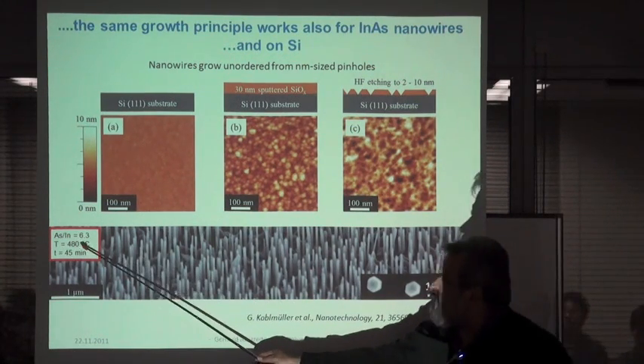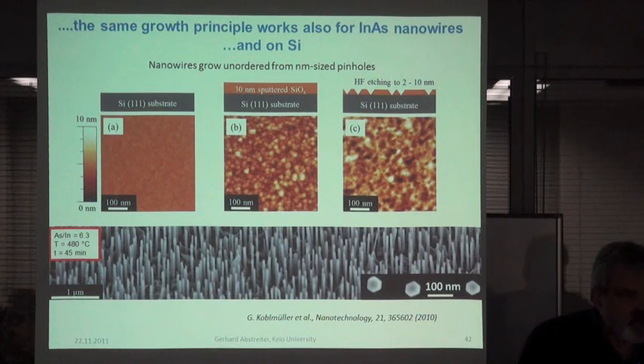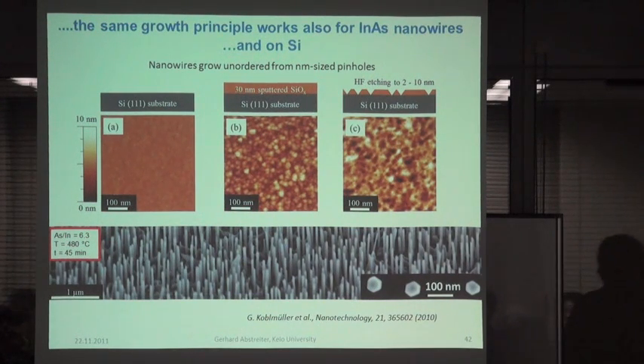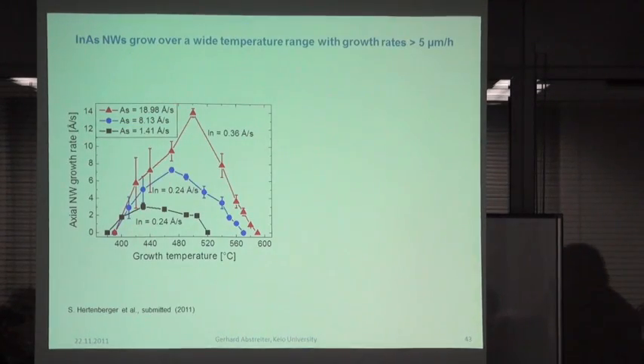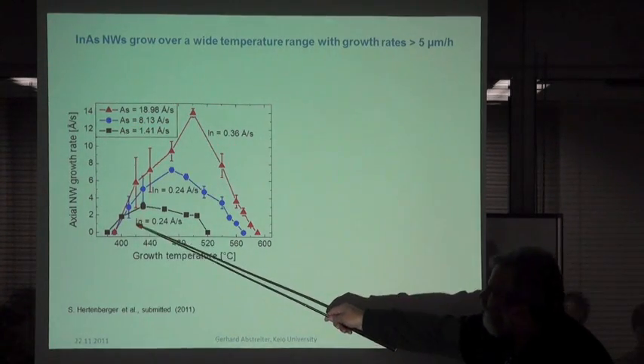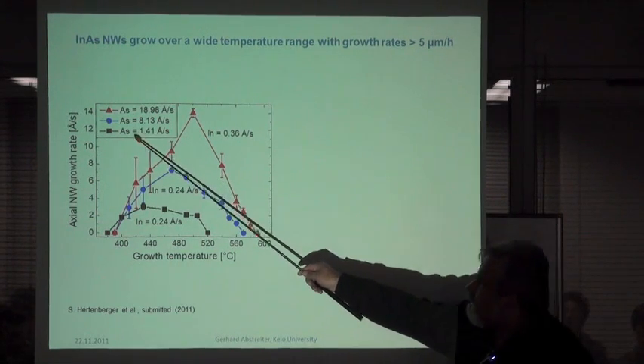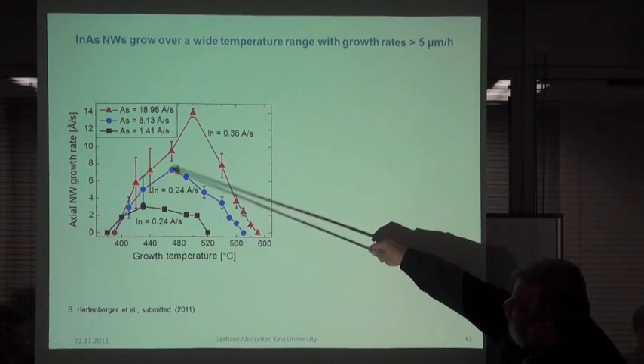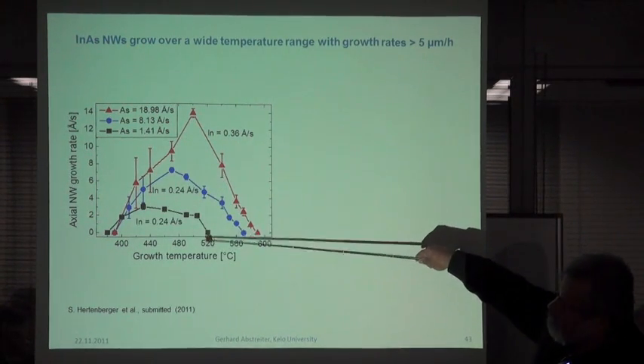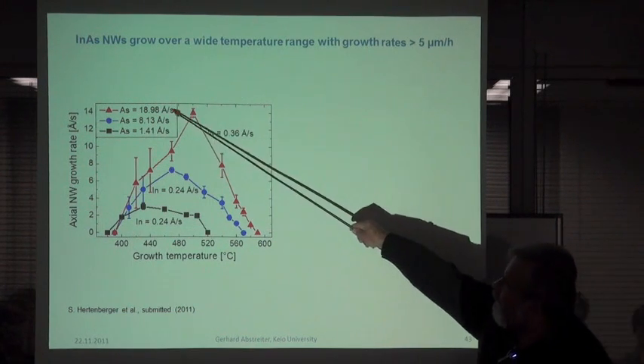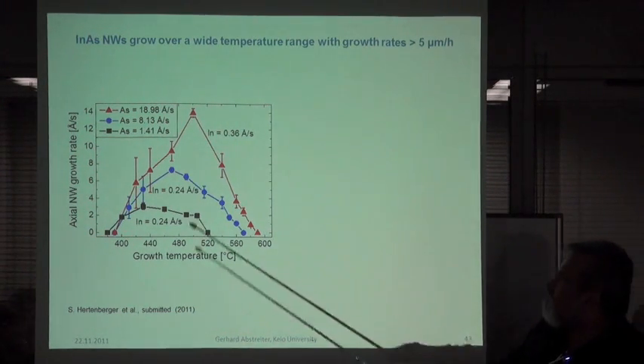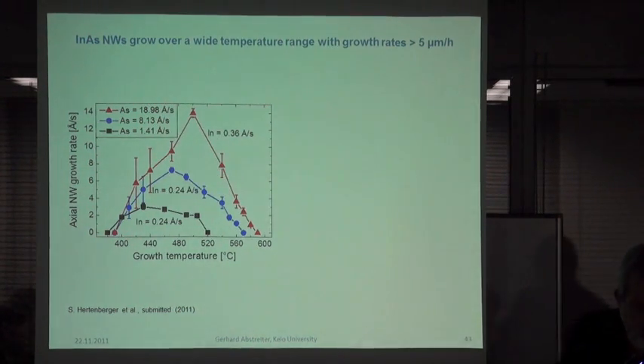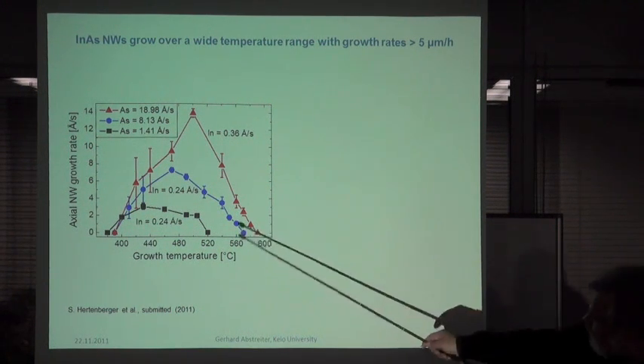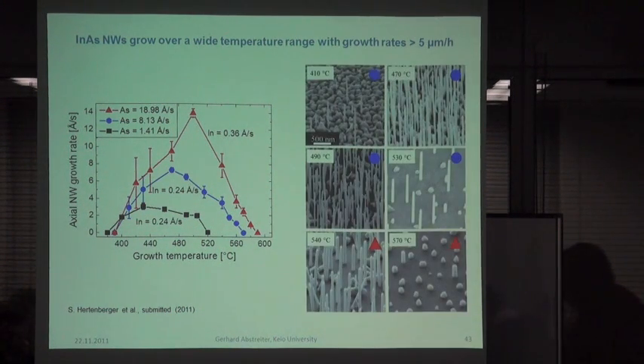However, for indium arsenide, this is for materials people, we need a lower temperature. Instead of 600, we need 500 centigrade, about 100 lower. But actually, in indium arsenide, we have a relatively broad range. It depends now on the arsenic pressure, and this is the axial nanowire growth rate depending on temperature and some parameters. So it's determined mainly by the arsenic flux, and we have a wide range for these indium arsenide nanowires.